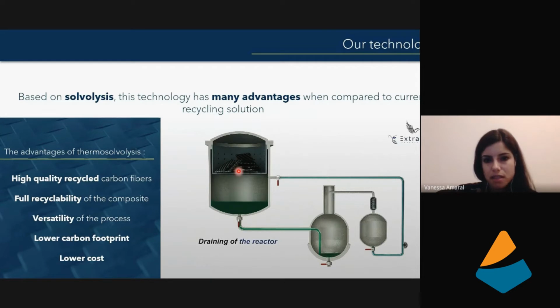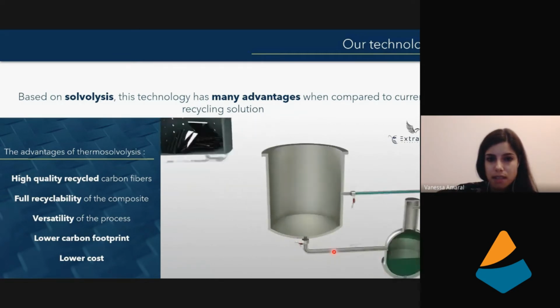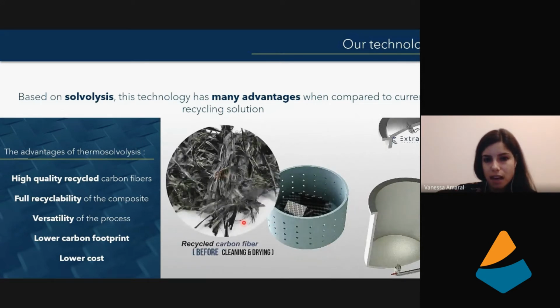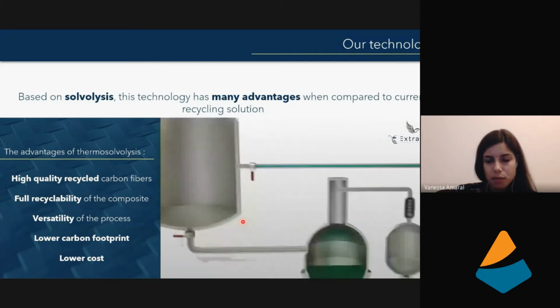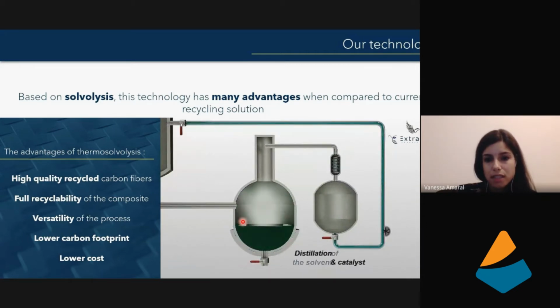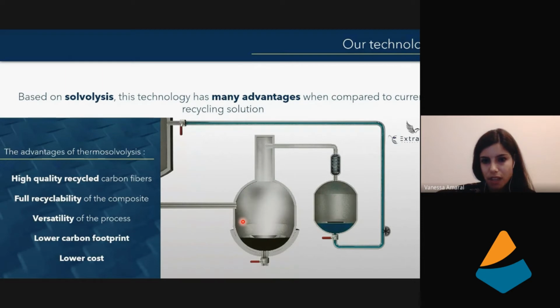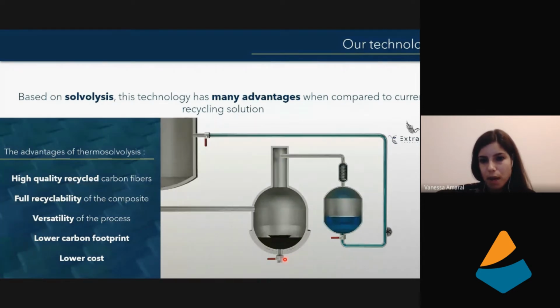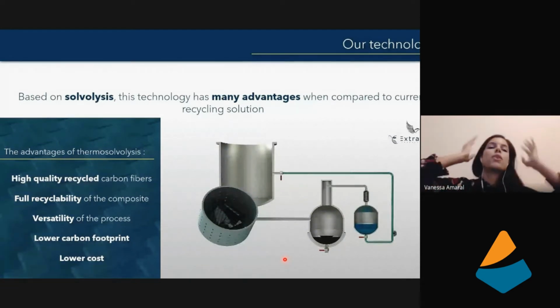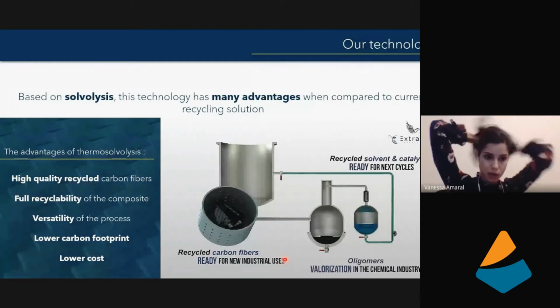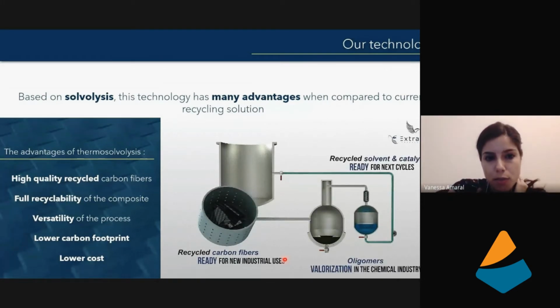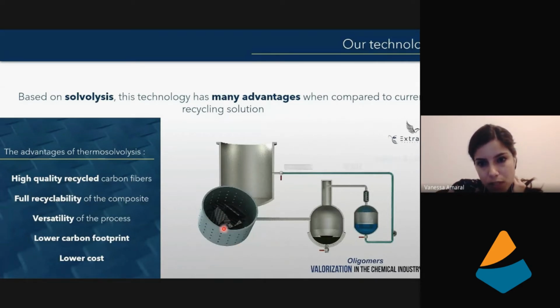So after the solvolysis process, we're going to recover the solvent, the catalyst, and the oligomers of the degraded resin. And in the basket, we're going to have these carbon fibers that are ready for the washing steps to be valorized. The chemicals are then going to be distilled. So it's just a simple process of distillation where we can recover the solvent and the catalyst for a new use, so they don't need to be disposed. And through this distillation step, we can recover the oligomers that are then going to be sold as a byproduct for the chemical industries.